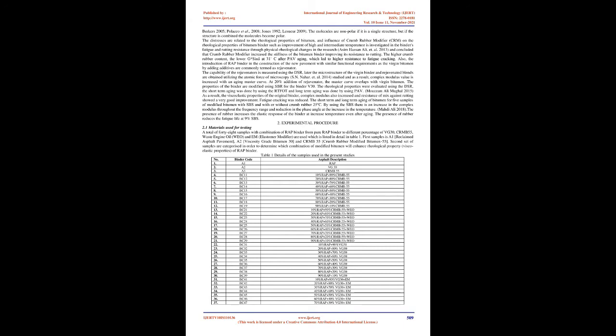By addition of crumb rubber, we observe an increase in softening point and reduction in the brittle point. There is also significant improvement in resilient modulus (MR), stiffness modulus, and increased stability and fatigue life. Results showed that CRM has a significant effect on bitumen rheology — it increases complex shear modulus G* and decreases phase angle. It is necessary to study the viscoelastic property of bituminous binders and their time-temperature recovery when applied load is removed. Aging affects pavement performance and hardens the pavement surface as temperature increases.